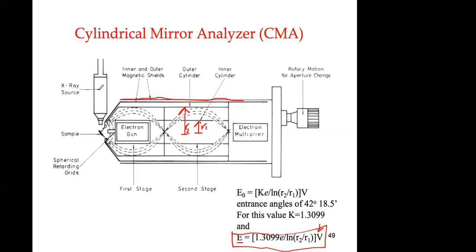In this design, they have the X-ray source and they have an electron gun aligned with this cylindrical mirror analyzer. This electron gun is used for Auger electron spectroscopy, and scanning Auger microprobe and nanoprobe. It's aligned very nicely with the analyzer. And the X-ray source is basically for XPS. I mean, you can do XPS with the electron gun, but the error of the energy of the electron gun is very large. So the full width at half maximum of your peaks in the spectra is going to be wider with an electron gun source compared to an X-ray source. That's why you use the X-ray source for XPS.